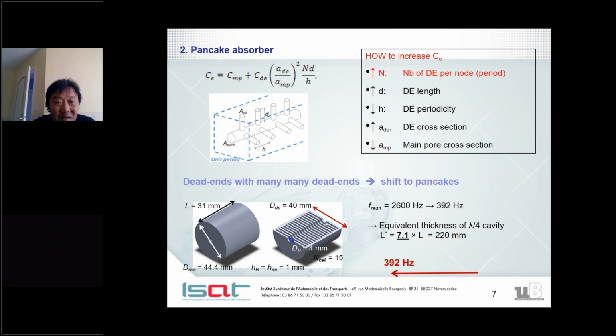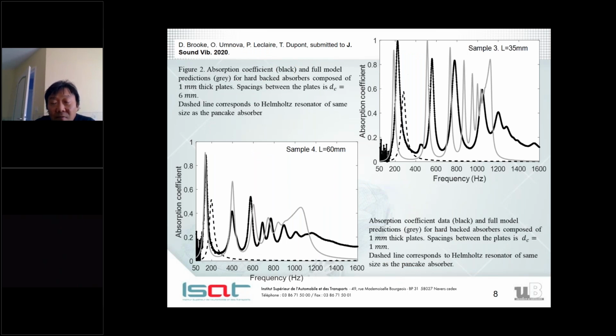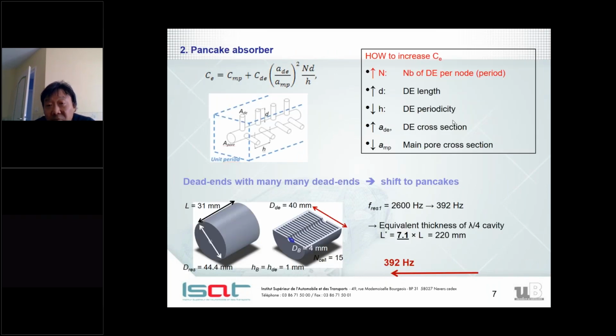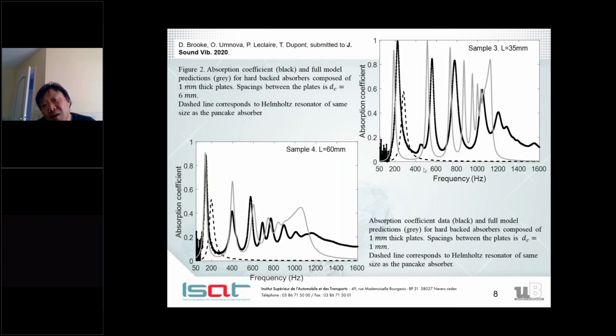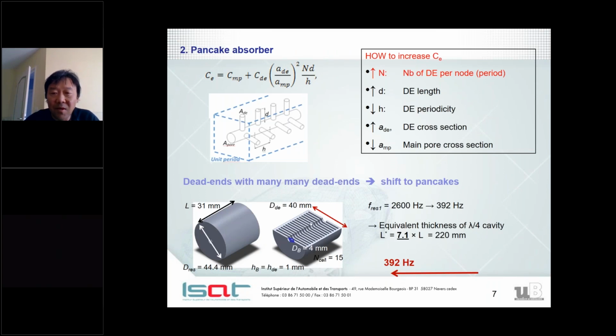So we went for this design and studied it numerically, analytically, and also experimentally. And here are a few interesting results. What is important is the thickness of the samples, resulting in the design of the multi-pancake design with the central perforation here. And the resonance frequencies are quite interesting because they are very low for the given thickness. And the analytical model is based here on double porosity, one corresponding to the porosity of the pancakes and one corresponding to the porosity of the main pore.